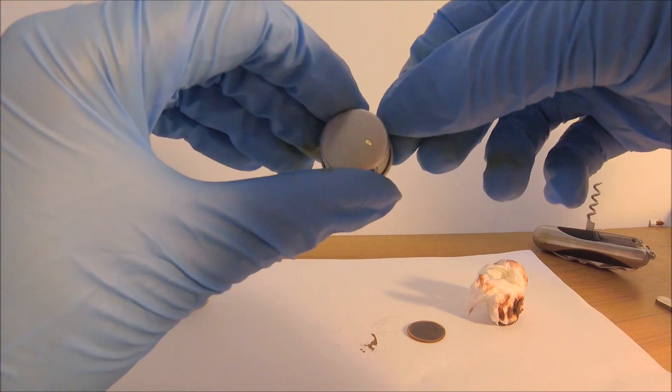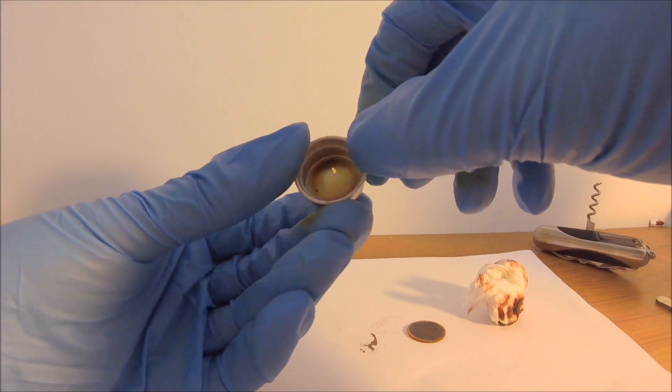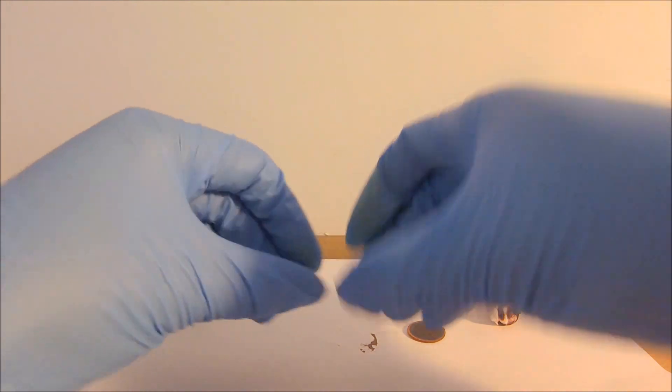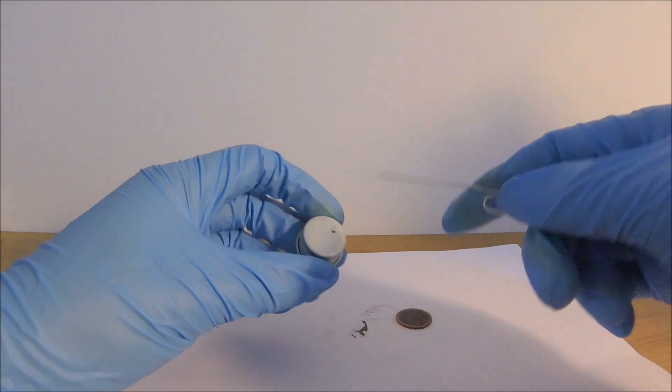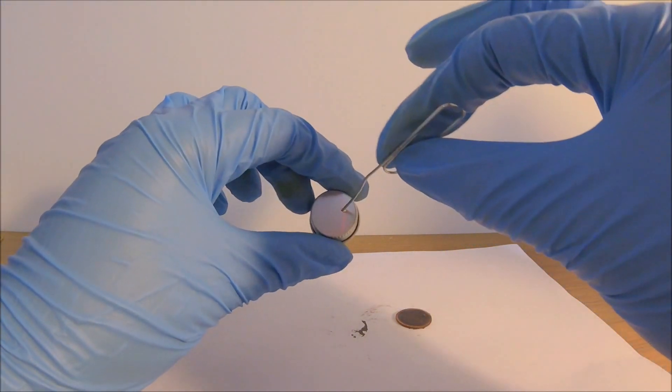Okay, this is very bad. I know full well that iodine reacts with aluminum, but I thought the polymer liner would act like a barrier to keep them separate. Okay, this is a confirmation here. It corroded a hole clean through the cap.